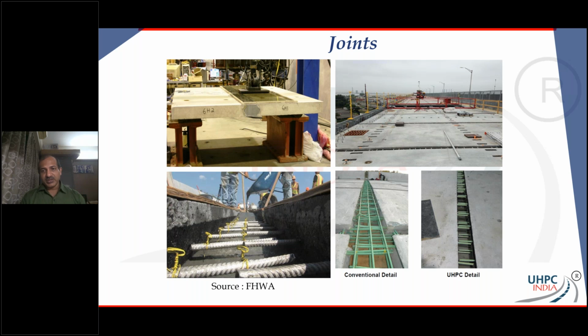Now, if anybody remembers, I just said a few minutes back that with UHPC, the development length of the rebar is just about 15 times the diameter, and that's why you have this slim UHPC joint. And anyways, UHPC is so much better in its properties that your joint is never going to go bad. Typically, in every project joint is the typical problem, but once UHPC is in, it's not going to be a problem anymore for you.